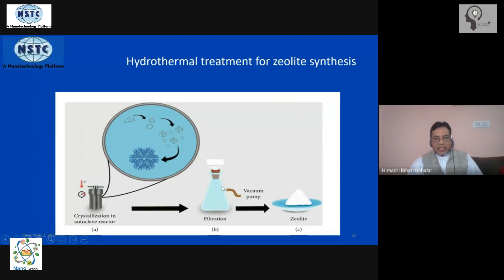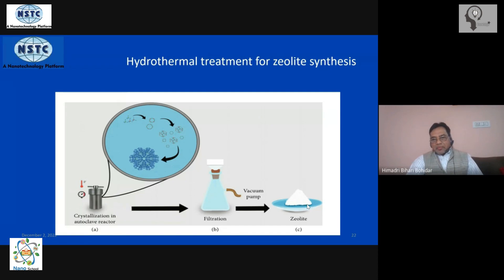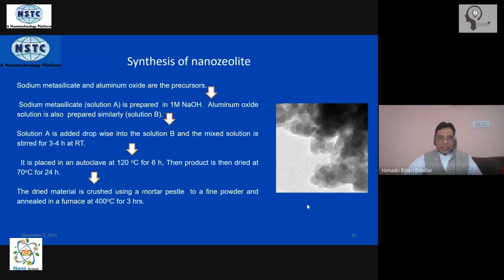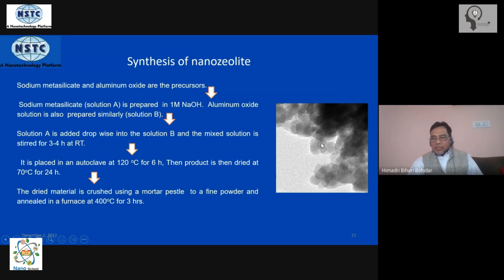After the reaction is over, you filter the material and you will see a beautiful white powder — that is the nano-zeolite you have synthesized. The synthesis process is very straightforward and does not require extensive infrastructure or high-end equipment, and the precursors are not very expensive. This is a TEM picture of the synthesized nano-zeolite — you can see the zeolite nanostructures assembled together in large clusters.